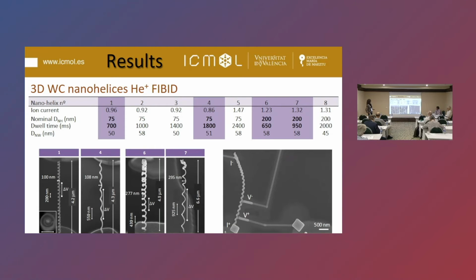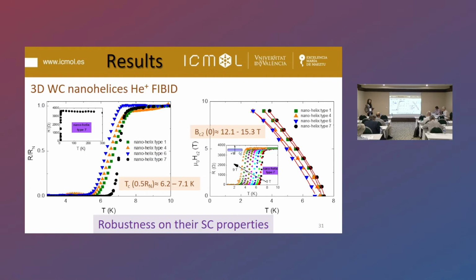Regarding the superconducting properties, I selected these four nanohelices, in which I can compare the same diameter, the smaller one, 100 nanometers, at different turn lengths, and another nanohelix diameter of around 300 nanometers with different turn lengths. I studied those superconducting properties using magnetotransport techniques, and I obtained very similar superconducting properties in all of these nanohelices in terms of the critical temperature, the upper critical magnetic field, and even the critical current density that I am not showing here. This gives us an idea about the robustness of the superconducting properties of nanohelices with completely different 3D geometry.